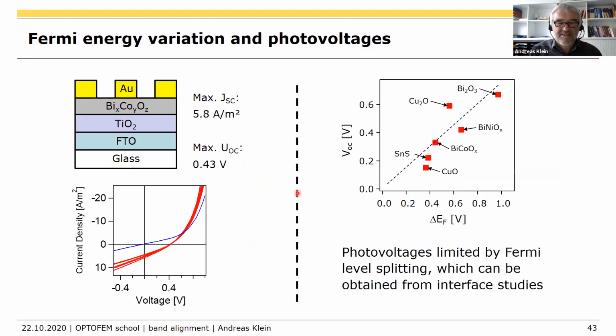Just to convince you that this is really important, here are some experiments, just some simple sketch, how we made some films, how we made the solar cells, and we measured efficiencies and photovoltages. And the photovoltage you get is pretty much related to the maximum splitting of the Fermi level we see in our XPS measurements. So our experiments can really reveal how high we can go with the Fermi energy and also how low we can go with the Fermi energy. And understanding this is really very important for making good devices.